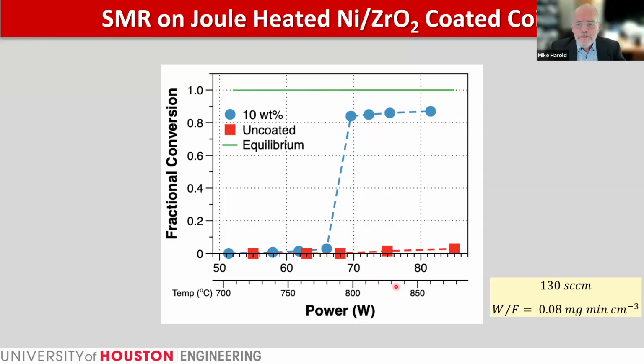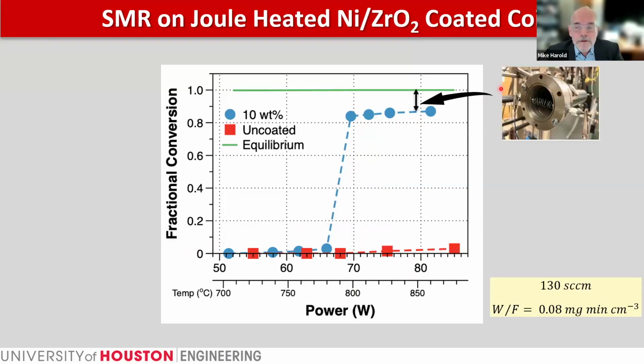Now, you can see, obviously, the catalyst has an important effect. Without the catalyst, the wire is basically inactive. Interestingly, we observed this sudden discontinuity in the conversion versus the imposed power or temperature that was kind of an unexpected result. We went into the experiment thinking we would get a kind of nice, smooth sigmoidal curve from a low conversion regime to a high conversion regime. Now, the focus of this talk is going to be on this discontinuity in large part, as you'll see as I walk through the data.